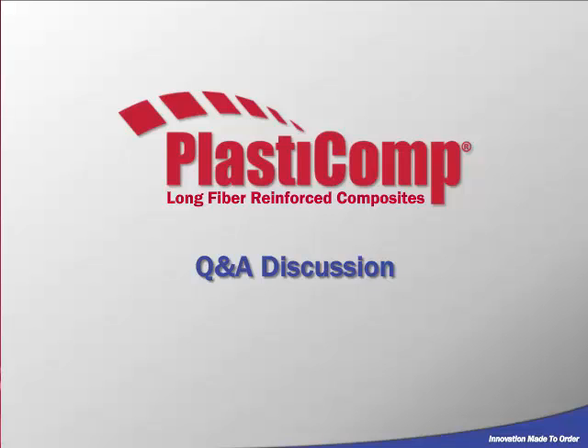Anything to add, Mark Henry? Yeah, as Eric said, it also depends on the part size and what the surface condition is that is interfacing with that gate. Larger is better. It depends what you're okay with when it comes to the fiber breakdown too. If you have a smaller part, you can also have a smaller runner because you have a smaller flow length, so overall you're getting less shear on the part. So that 1/4 inch was a good reference to think about. Thank you.